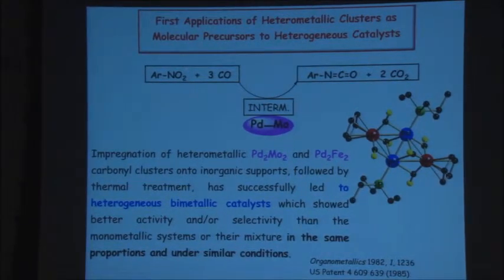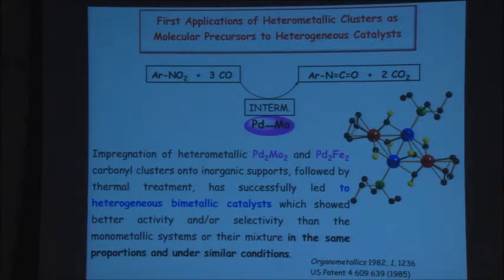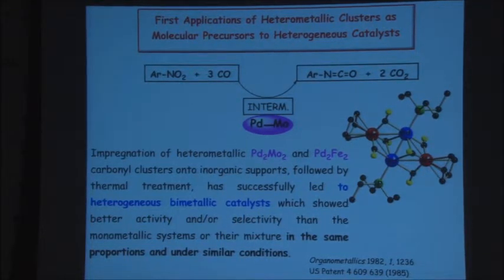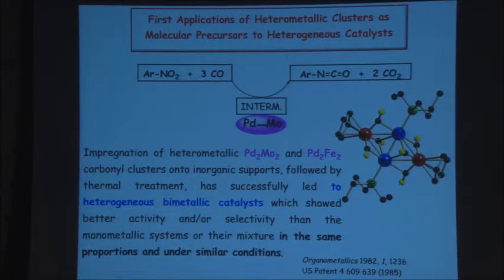And nitros would be a good candidate because they are usually the precursors to the amines. So if you take the phosgene route, you first have to reduce nitros to amines anyway, which is costly, and then use phosgene. Carbon monoxide is cheap and readily available. So that could be the reducing agent and form directly the isocyanate. So I said to the company, try our catalyst versus your own catalyst. I don't want to know what you put in your system. Just make sure two things. Everything should be run under comparable conditions. If you add salt and pepper at some stage, add salt and pepper to our catalyst as well. But keep the same metal ratio as we have here, 1-to-1 ratio, to be really comparable. And our system turned out to be better.